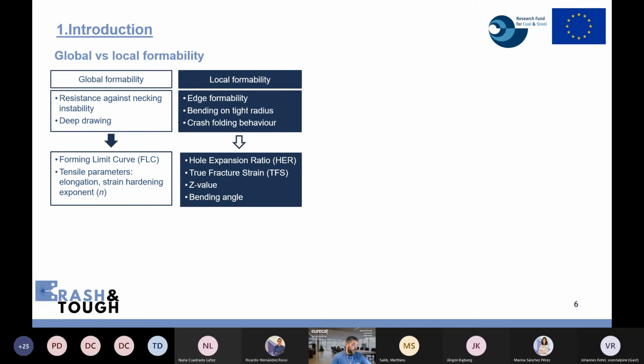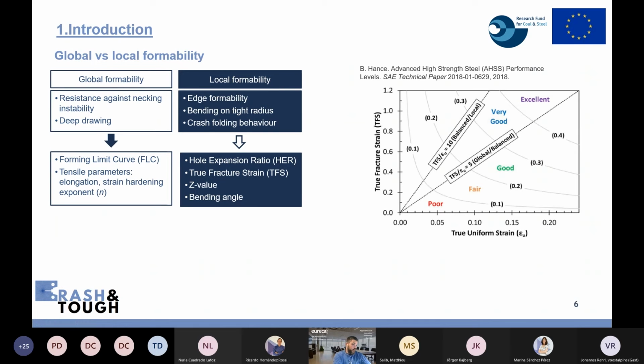For representing the local formability of advanced high-strength steels, different parameters have been proposed in the last years, like, for example, the hole expansion ratio, which is well known and well established for edge cracking resistance measurement. Also the true fracture strain from the uniaxial tensile test, measured from a reduction of area from the fracture surface of uniaxial tensile specimens, or the bending angle from the bending test according to the VDA. Also based on these new parameters, even new and advanced classification maps for advanced high-strength steel have been proposed, like this Hance diagram, where the true uniform strain is represented as a measure of the global formability, while local formability is represented by this true fracture strain.